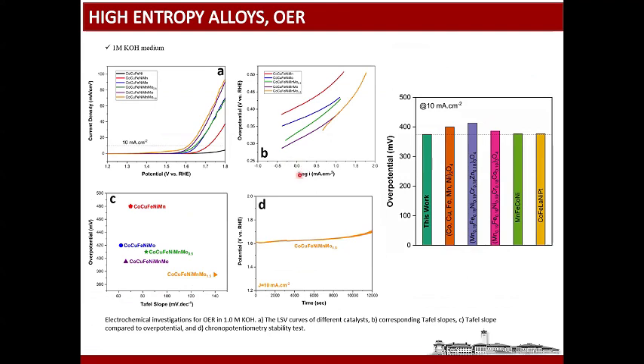So we did the electrochemical test. The one with the molybdenum 1.5 composition has the lowest overpotential, as you see here, and it also showed the highest activity. So we compared our work with those in the literature for the oxygen evolution reaction, and we have one of the lowest overpotentials in the literature. And then we also did the stability test. Of course the overpotential changes over time, but the change is not that significant. So it works.